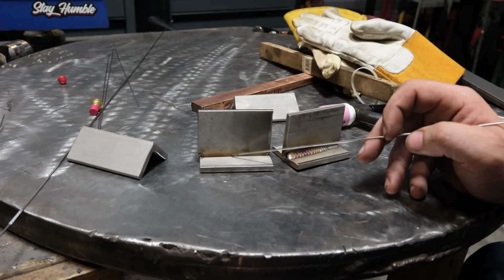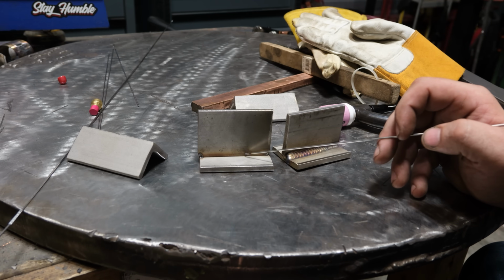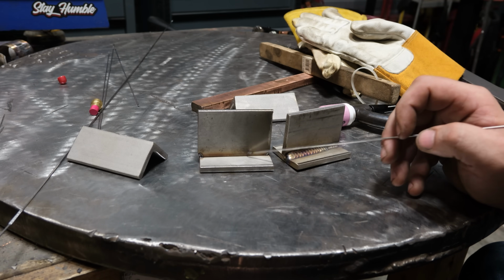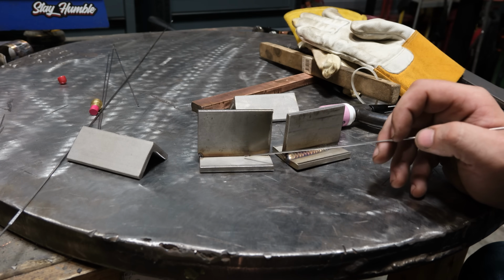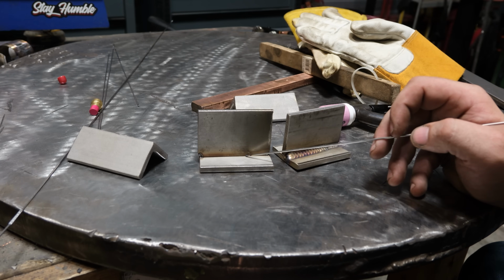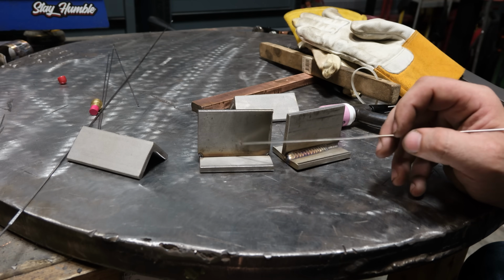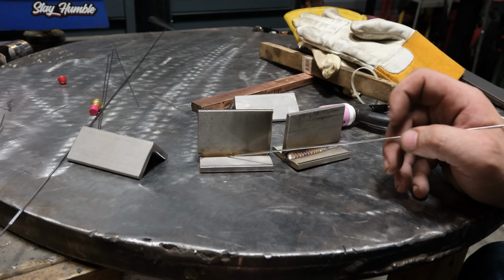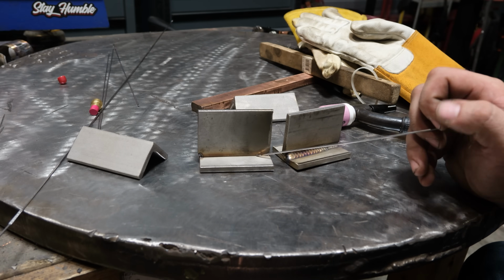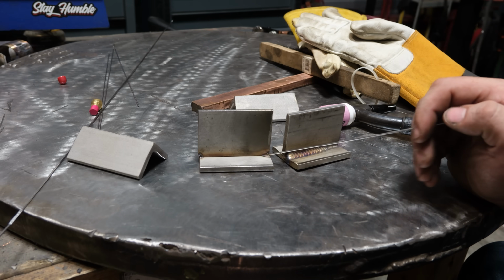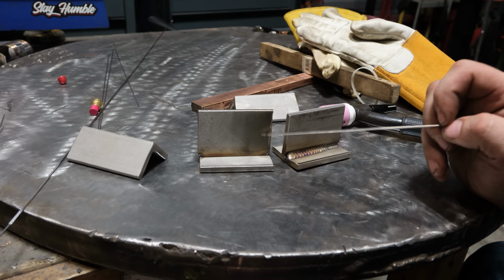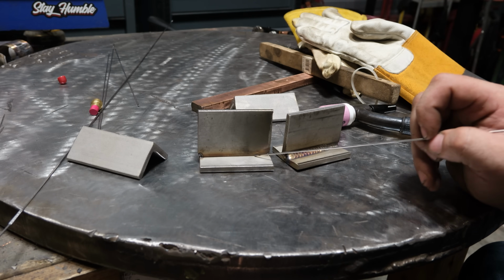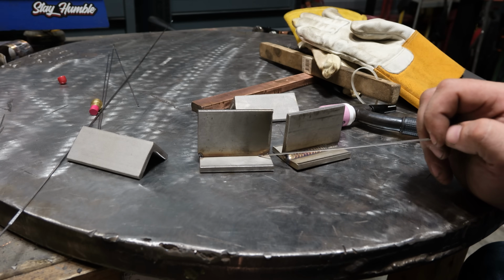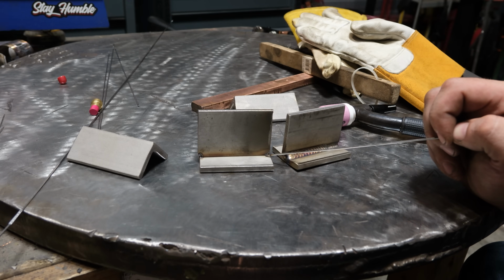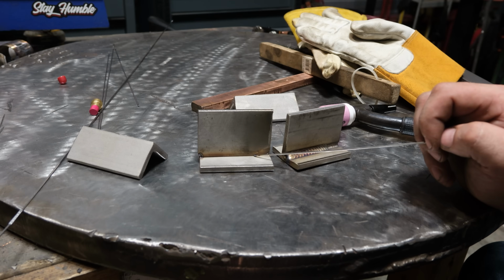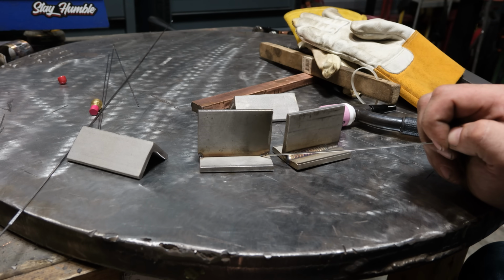One of the things you guys got to understand with this material is it's a very poor conductor thermally speaking compared to steel and even aluminum, but we'll compare it to steel. And because it's a poor conductor, it actually takes a long time for thick stainless to get hot on the backside to where it would react with oxygen. Therefore, on thicker stainless, it's generally a lot less critical to have a back purge. No doubt, if I were to break this, there's some level of oxygen contamination underneath that, and I will do that in a second just to see. But it probably won't be that bad, and realistically, from a strength perspective, it's not going to be a detriment, I don't think.